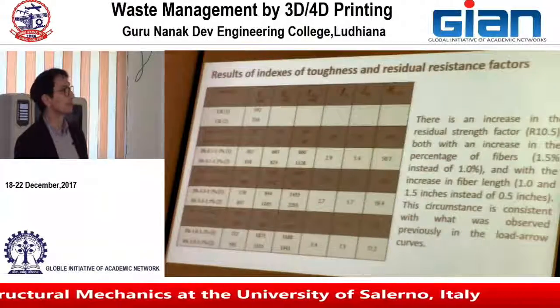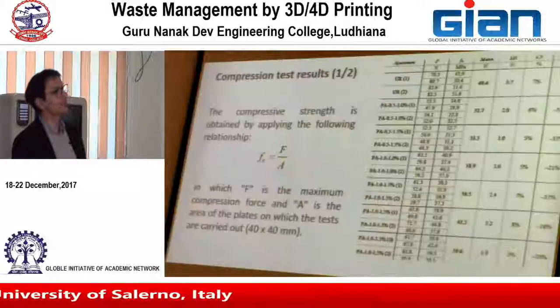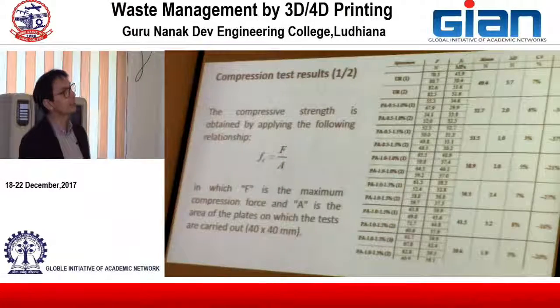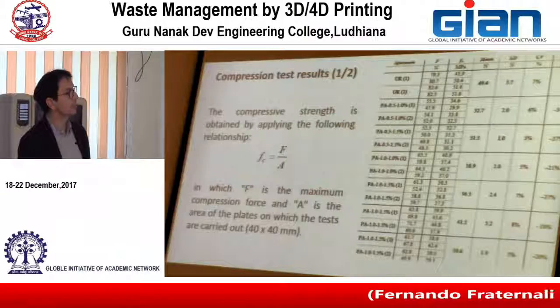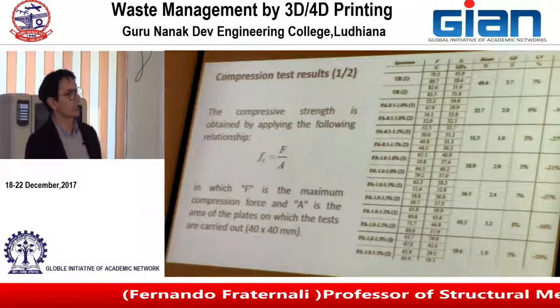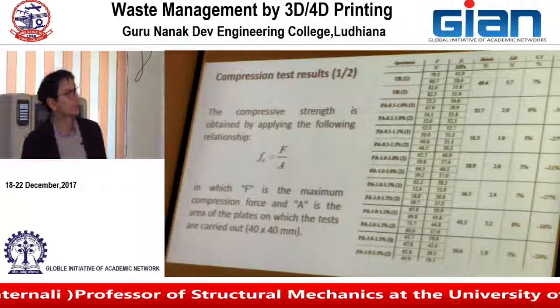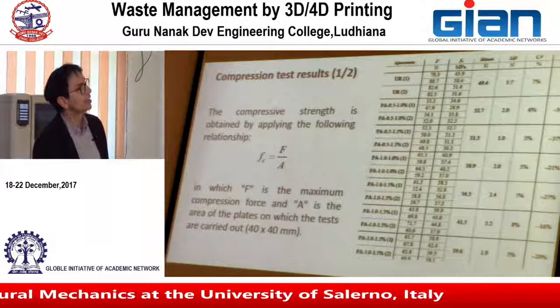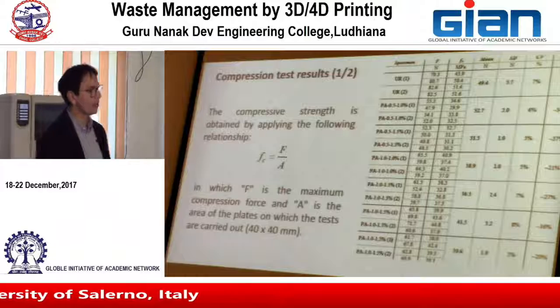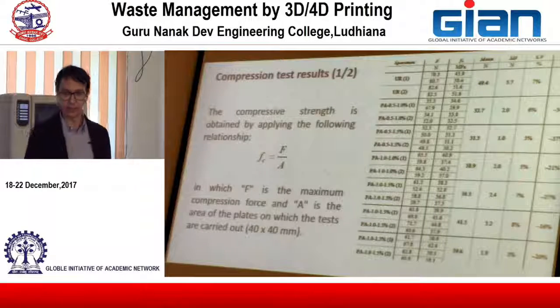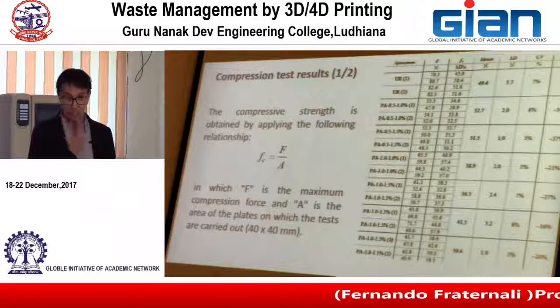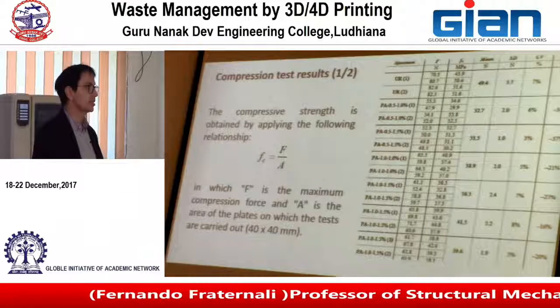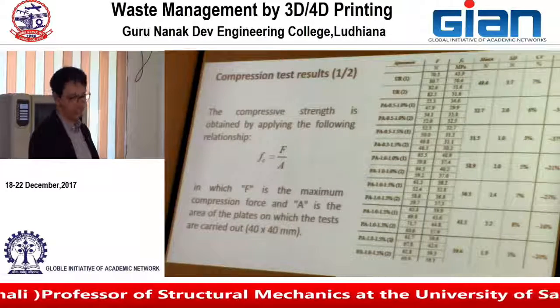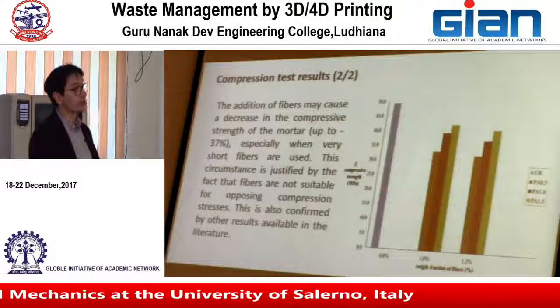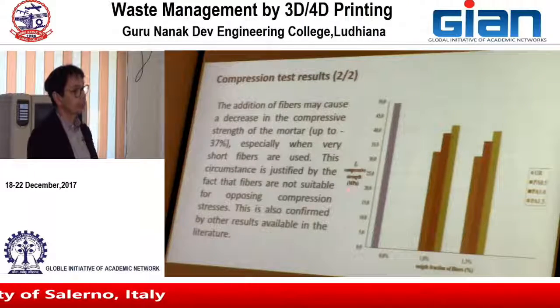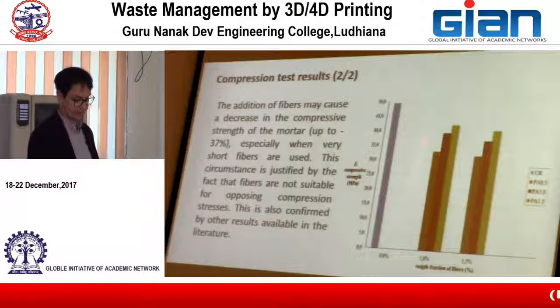We also carried out the compression test, and in the case of the mortars, we observed a decrease of the compression strength, which is usually standard. You usually obtain reduction of the compression strength and increase in the bending strength. Indeed, this was the case. We had a reduction of the compressive strength in all the examined specimens.